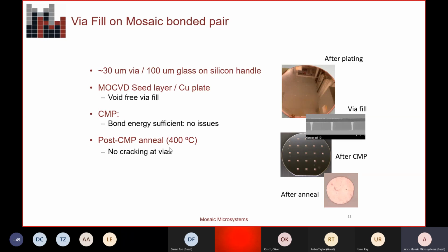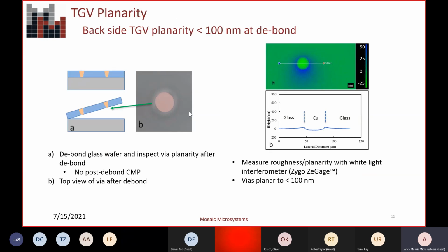And then we annealed these wafers to 400 degrees C, and again, you don't see any cracking around the via. We inspected every single via on this wafer, and there was no cracking that you would see if there were voids. So a very good demonstration of interfacing with the processes needed to enable thin glass devices.